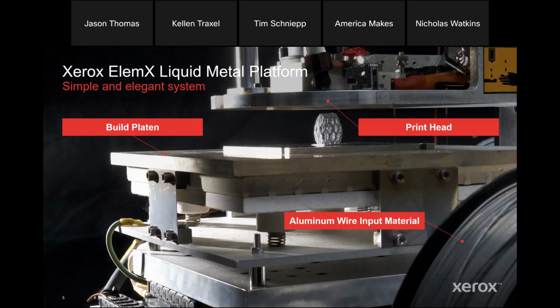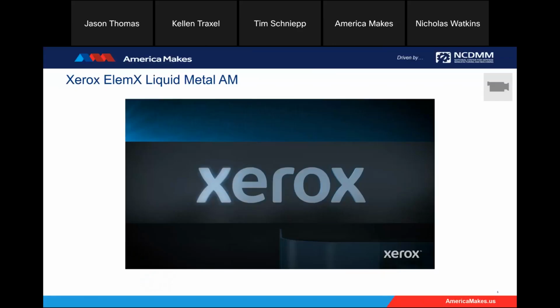So you can see here, it starts with a spool of aluminum welding wire, aluminum wire, and then analogous to an FDM polymer AM system, that wire feeds up into a heated head. We melt the material with resistance heaters. It's held in a molten state in a little ceramic crucible within the head. And we use electromagnetic jetting to dispense a continuous series of droplets onto a heated build plate. So you see that here. And I'll show you a video here in just a moment that gives you an idea kind of how that works. Now, this is the first of two videos that I'll show.